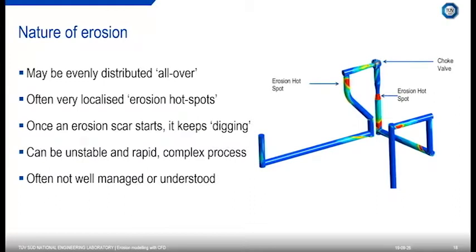So on the right-hand side, I have a CFD prediction of a Christmas tree configuration. This considers the number of blind tees that we have here, bends, choke valve, venturi. And you can see in terms of the colours for CFD, where red is high spots, we have quite a number of hot spots, either caused by a roping effect as the flow is changing direction, or as it's accelerating through a venturi as it continues through this Christmas tree configuration.